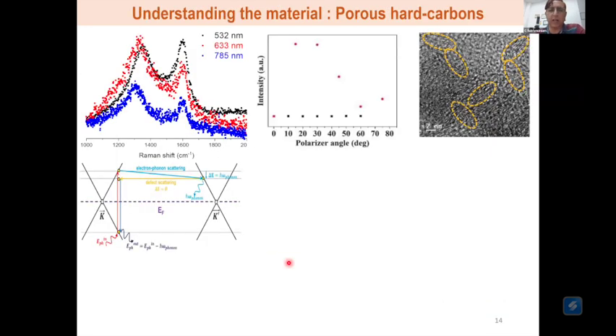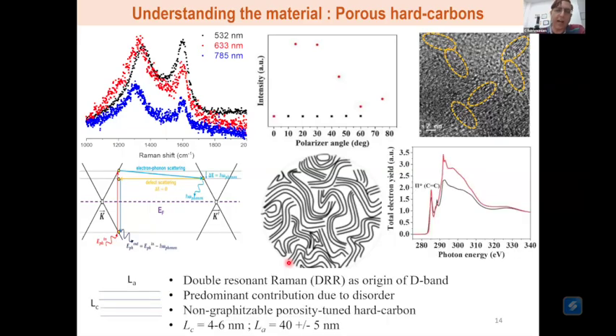And we have done a lot of spectroscopic and microscopic studies, and introspected the structure with a lot of complementary techniques, to arrive at the final structure, which is basically a combination of short-range ordered, graphitically ordered domains, which are in turn disordered in the long range. This kind of structure is called a hard carbon structure in the literature. What is already known is that it's a hard carbon structure, but what we have done on top of the hard carbon is induce these well-defined pores to give it that particular morphology, which is very important.